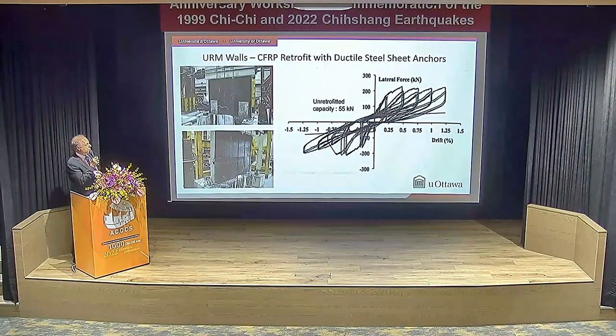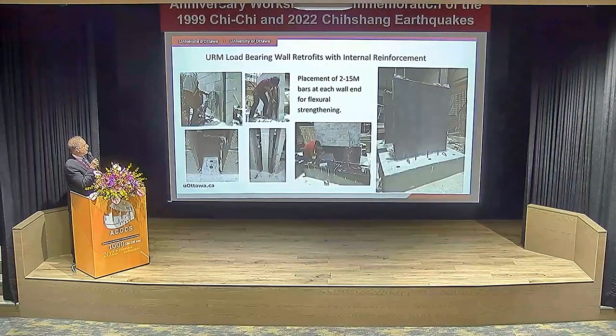And this is the comparison. The companion specimen had very weak resistance as being unreinforced masonry, and we only got 55 kilonewtons as opposed to about 200 kilonewtons resistance after this retrofit. And there was some ductility and energy absorption capacity, and not only that, but the steel was able to, not all the steel yielded, was able to bring the specimen back to the origin as well.